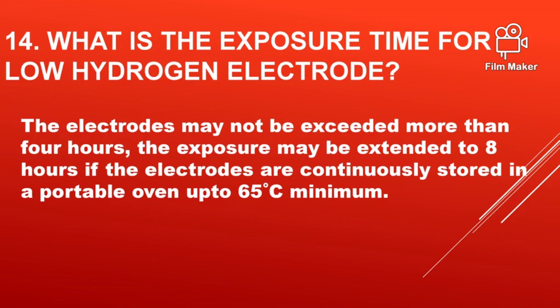What is the exposure time for low hydrogen electrodes? The electrodes may not be exposed for more than 4 hours. The exposure may be extended to 8 hours if electrodes are continuously stored in a portable oven at a minimum of 65 degrees centigrade.